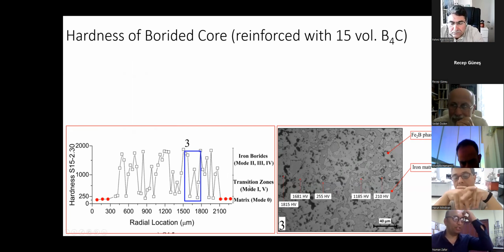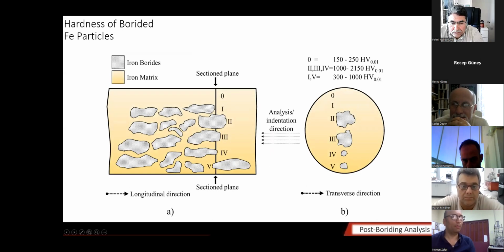But I want to take your attention to something, because this thing is not that simple. On the low side, you see the hardness of the iron matrix and the sheath. And up, you see the hardness of the iron boride phases. There are these transition zones, mode 1 and mode 5, which have a hardness in between these two. This is because the microstructure is distributed in such a way that, no matter if you see this picture, it is taken schematically, prepared for the longitudinal direction, and this is from the transverse direction.